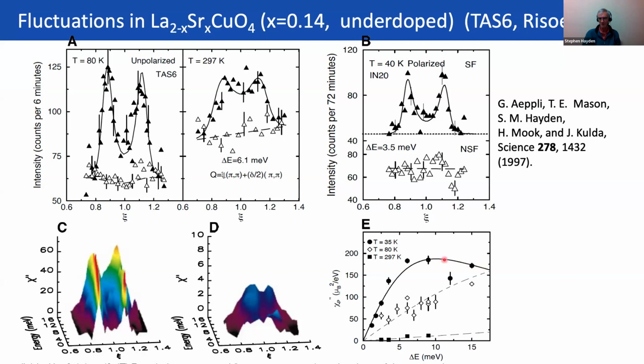So on the underdoped side, if we were to read off an energy scale here, we'd say it's about 10 meV. So that's going to be higher than what I'm going to show you in a minute. I suspect now, looking back on it, that what appears to be a high energy scale is actually due to the pseudogap pushing spectral weight up from low frequencies. In fact, that's why we see this. Okay, so that's the underdoped side.